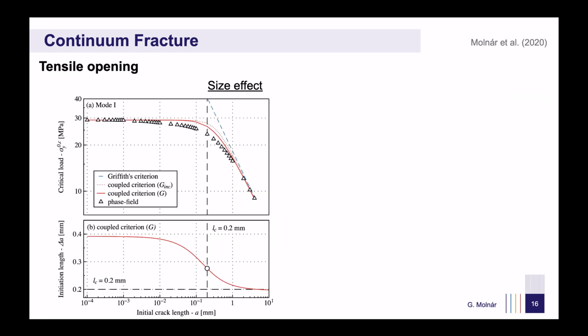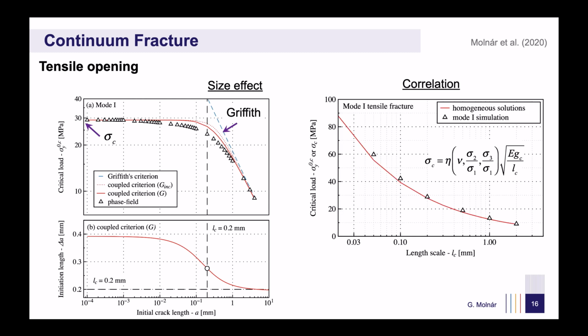By examining critical loading in mode 1, we find that both phase field simulations and the coupled criterion successfully reproduce the experimentally observed size effect. When the initial crack is large, the behavior aligns with Griffith's prediction. However, when the crack is smaller than LC, the failure follows a stress-based criterion. These results allow us to compare LC, the length scale used in phase fields, with the tensile strength used in the coupled criterion. You observe that as LC increases, the tensile strength decreases, a trend that can be perfectly fitted using the homogeneous solution of the phase field method.